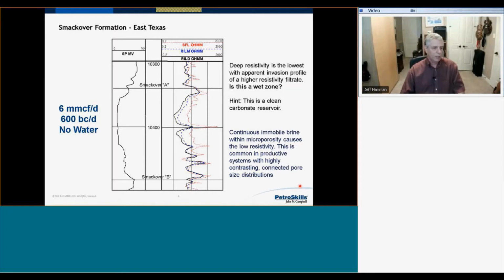No. This well was completed and produced at 6 million cubic feet of gas per day with 600 barrels of condensate and no water. The reason that the resistivity is low is because there is an immobile brine, high immobile brine saturation caused by a continuous microporosity.